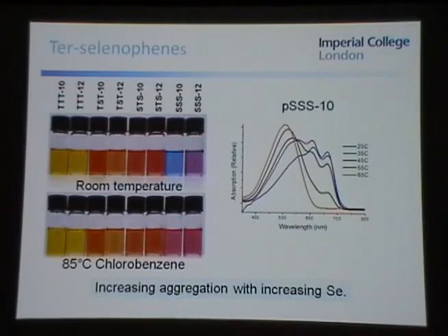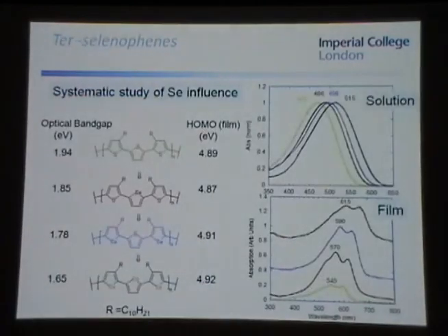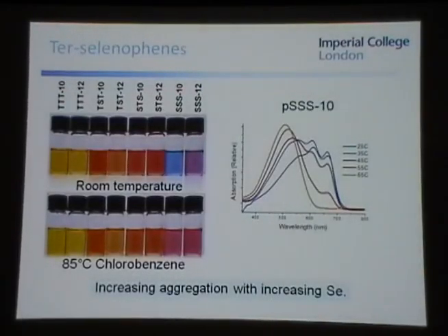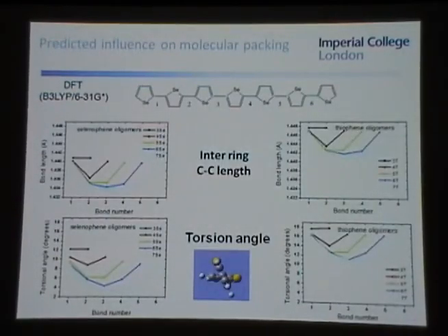So this is the UV spectra of this polymer, and it looks basically identical to the thin film. And that's because even in solution, the polymer's planarized and aggregated because there's more quinoidal character between the two selenophenes. Or the LUMO is lower in energy, in other words. So this makes the material more coplanar. You can also prove that with some DFT calculations.